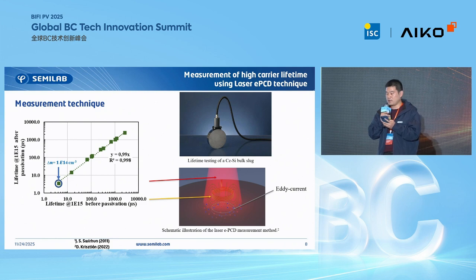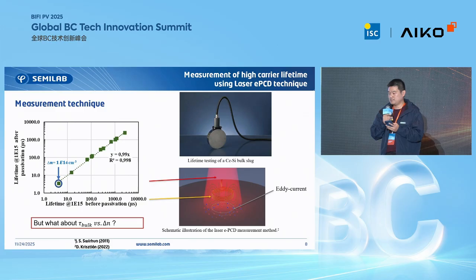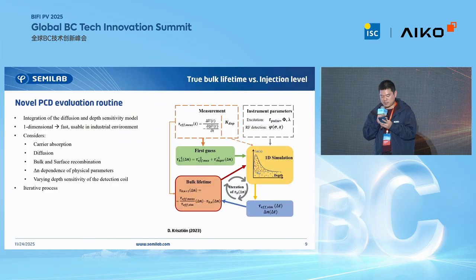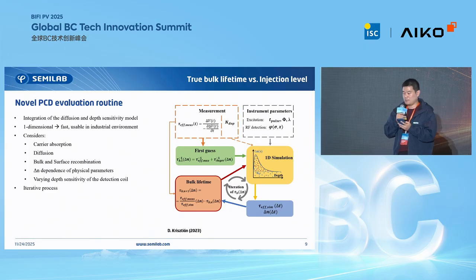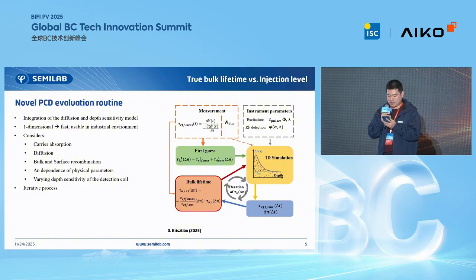However, for better characterization, not only the carrier lifetime, but its dependence on injection level is relevant as well. Due to the interplay of several physical phenomena, it is challenging to obtain on thick materials. Therefore, our scientists in Budapest developed a complex iterative simulation-based algorithm to provide this information. The model needs a couple of physical phenomena, like I listed here: carrier absorption, diffusion, bulk and surface recombination, and so on. It makes the proper evaluation very challenging.